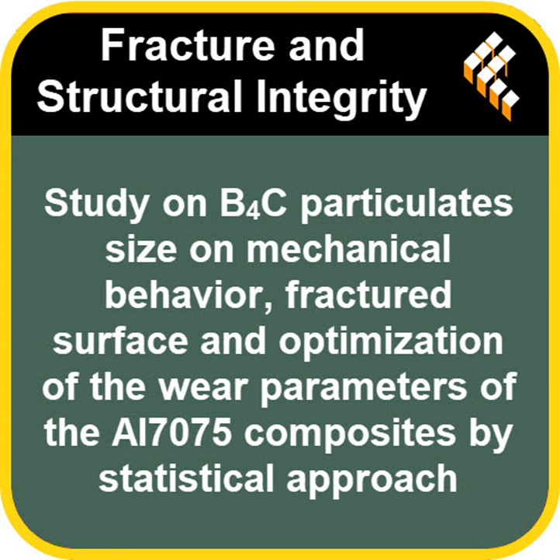Right. So what were the main findings on wear loss? How much material actually disappeared? Which ones held up best? Well, particle size was definitely dominant again. The nanoparticulates consistently showed better wear resistance. Less material was lost compared to the micro ones. And why was nano better for wear? Several reasons suggested. The fine particles are just more widely and evenly distributed. Their sharp edges might get dulled during the abrasion process itself, and maybe crucially, they seem to embed better into the matrix, making them less likely to get pulled out or fragment. That makes intuitive sense. Less likely to get ripped out.